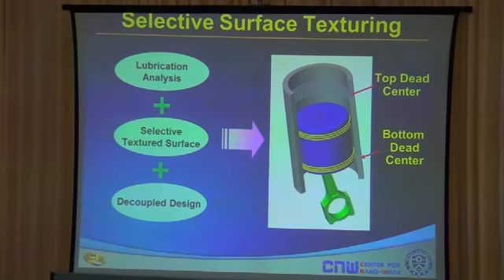And in the middle section, it travels very quickly, and the interface between the piston ring and the cylinder liner is separated by a very thin lubricant film. In this case, the lubrication condition is hydrodynamic, and we do not expect much problem in terms of friction and wear. However, at the top dead center and the bottom dead center, the ring stops momentarily, and you have pressure of the piston ring going against the cylinder wall, and this is when you go into mixed and boundary lubrication, and this is when you expect to have more problems.